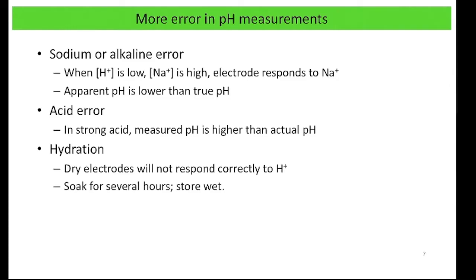So the apparent pH is going to be lower than the true pH because some of the signal from the electrode is coming from sodium. There's also an acid error. So in strong acid, the measured pH is higher than the actual pH. We don't really know why this happens, we just know it does. And hydration is also important for electrodes because dry electrodes won't respond correctly to H+. So when you're doing measurements with an electrode in lab, you should make sure that the electrode is in some kind of solution at all times rather than hanging on a clamp exposed to the air.